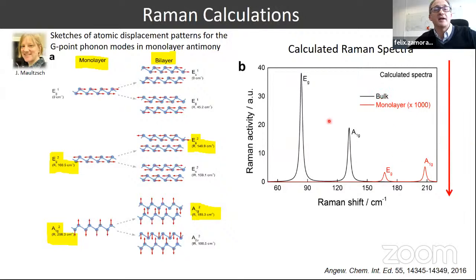Another important aspect is that she predicts an inversion in the relative intensity of the two signals, as you can see here, from the bulk to the monolayer. So this signal becomes more intense than the one corresponding to the Eg. Additionally, we observe a blue shift. All these calculations agree with the experimental observations.